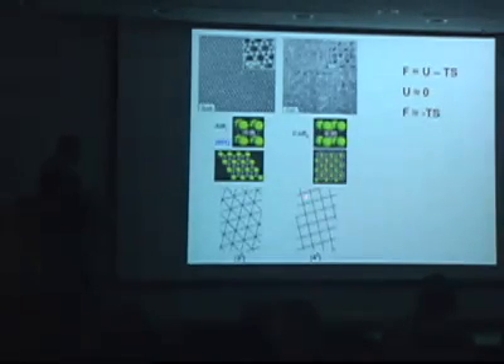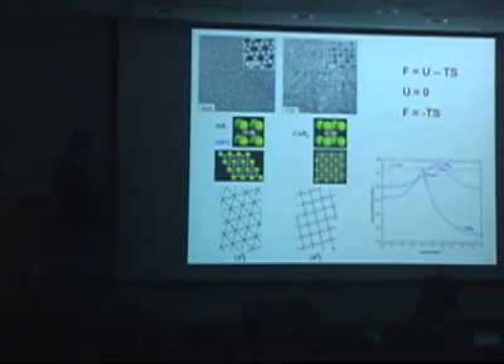Now, they can form under very similar conditions. What we can do next is try to match translational and rotational entropies associated with the self-assembly process for both structures. In hard sphere packing or sphere packing theories, there is a clear connection between entropy during self-assembly and the packing density, the space filling of the structure. The denser your assembly is, the higher the entropy gain during